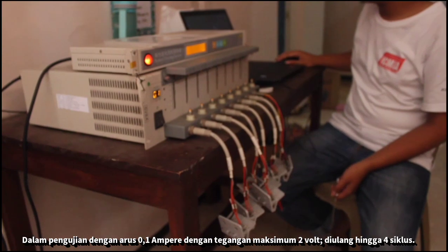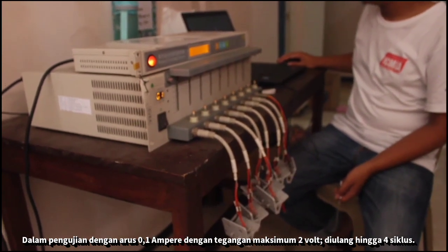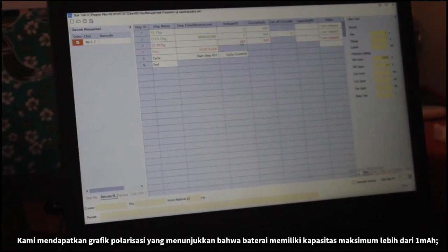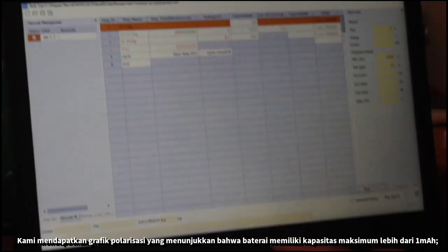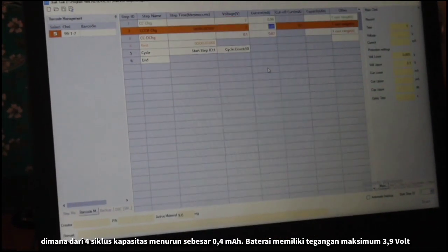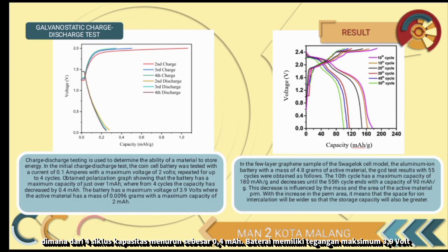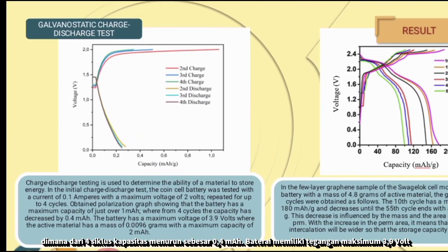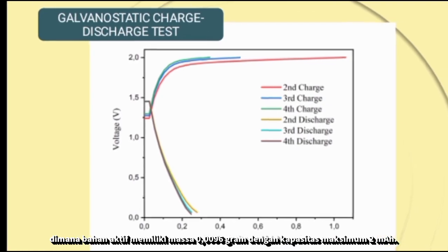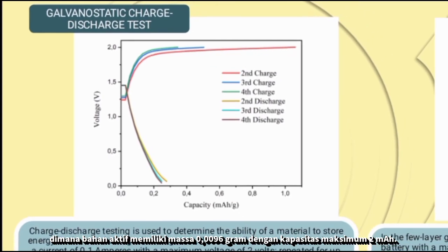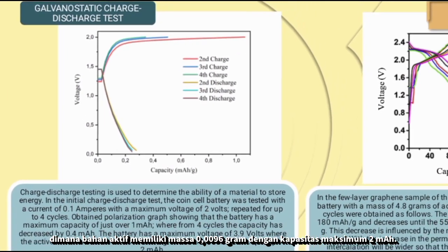In testing with a current of 0.1 amperes with a maximum voltage of 2 volts, repeated for up to 4 cycles, we get a polarizing charge showing that the battery has a maximum capacity of just over 1 milliampere hour, where from 4 cycles the capacity decreased by 0.4 milliampere hour. The battery has a maximum voltage of 3.9 volts, where the material has a mass of 0.0096 grams with a maximum capacity of 2 milliampere hour.